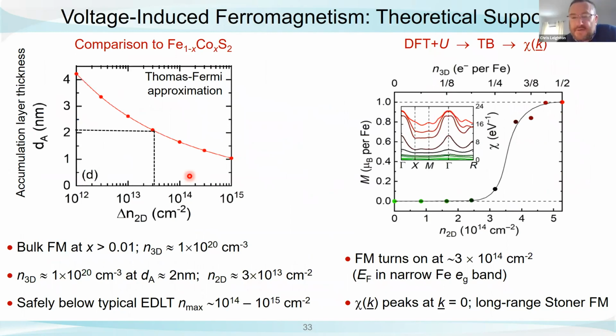We've also done some theory on this in collaboration with Taran Barol and Rafael Fernandez. I won't go through what's on the left. That's basically bookkeeping. We did check that the amount of charge that should be necessary to do that is conceivable in comparison to cobalt-doped iron disulfide, so that's a little bit dull. What's more interesting is we did some DFT plus U calculations where we calculate the magnetization that should happen in this material as a function of just adding electrons to the iron sulfide unit cell. And when you do that, ferromagnetism does turn on. It actually becomes highly spin polarized. You go up to 1 Bohr magneton per iron eventually. That happens at about 3 × 10^14 per centimeter squared.